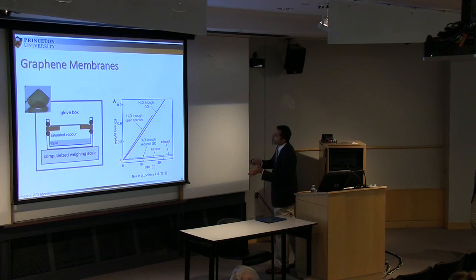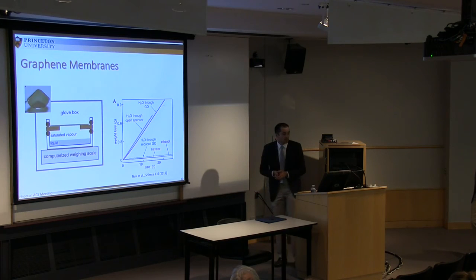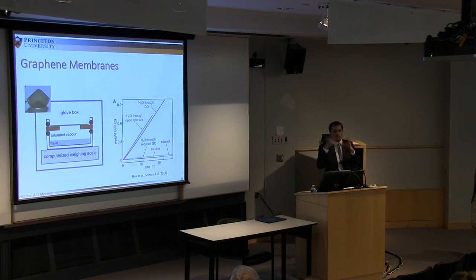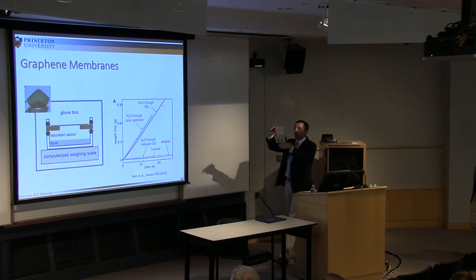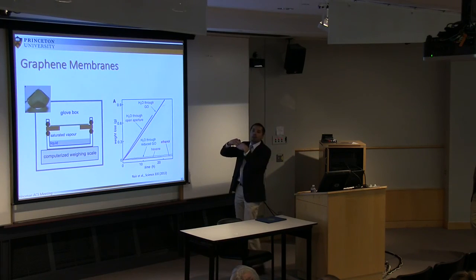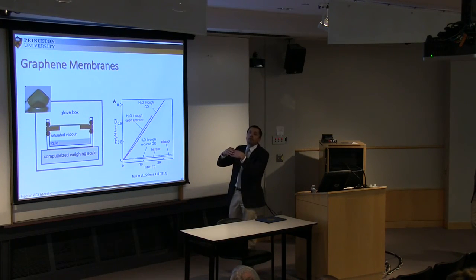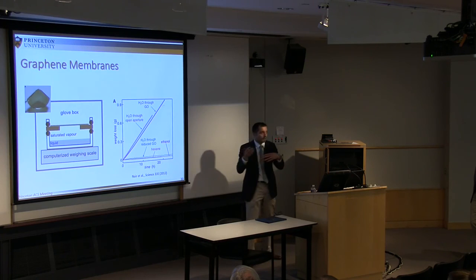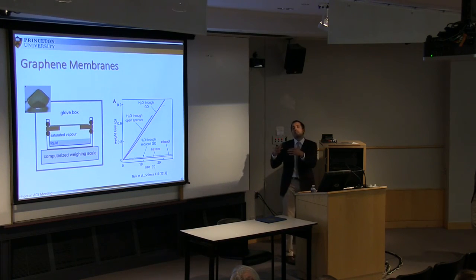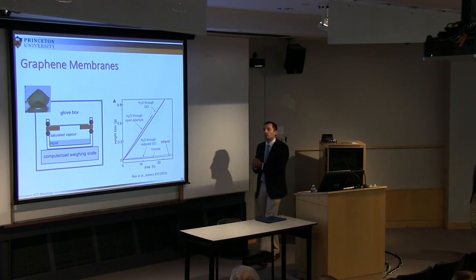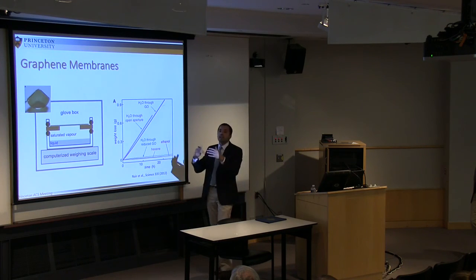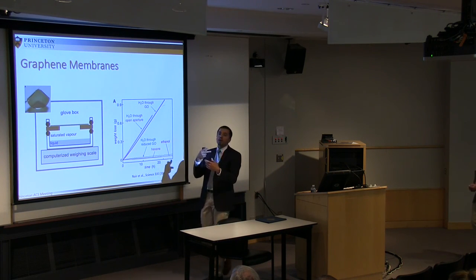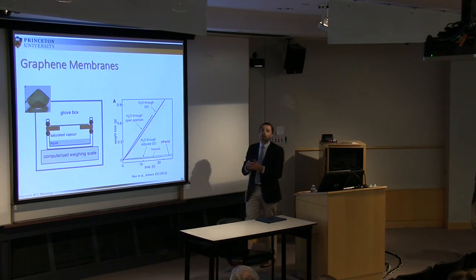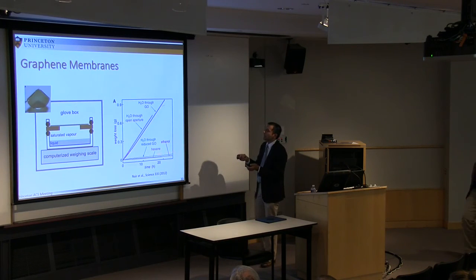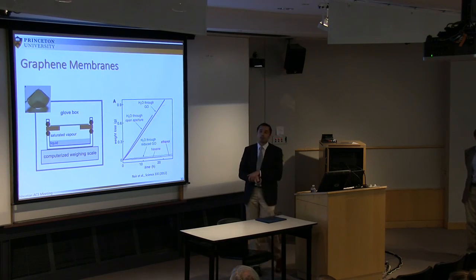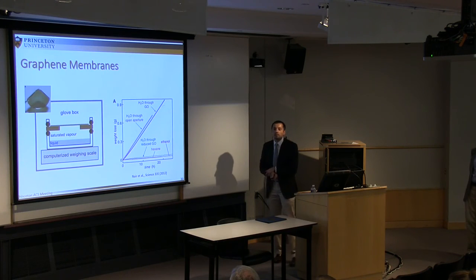You have water that goes through, but now if you heat this, so you basically get rid of the oxygen groups, you make the graphene sheets collapse. So the graphene structure has changed because you not only have removed these functional groups, but you also have changed the lattice of the basal plane. So that makes it less compatible with water, and therefore you can now have an effective barrier for water. Did I respond?